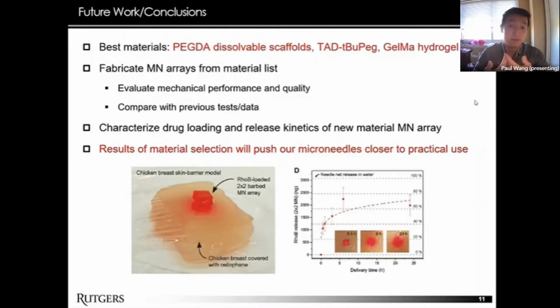So based on the material study and our selection process, I determined the best materials for fabrication would be the PEG-DA dissolvable scaffolds, the TAD-T-Bu-PEG, and GelMA hydrogel. The next steps for the project would be fabrication. The materials selected will be used to fabricate the microneedle arrays and evaluate their mechanical performance and quality, and we compare the results to our previous tests. After that, we can characterize the drug loading and release kinetics of the new material microneedle array.